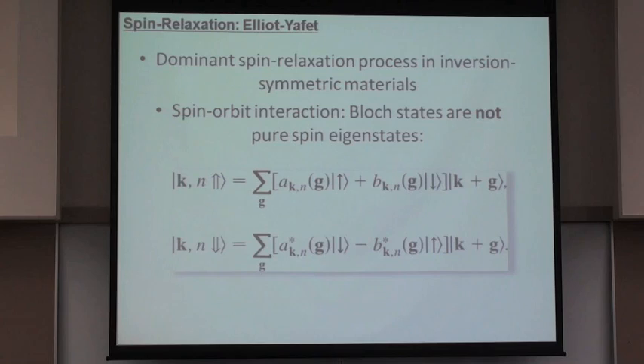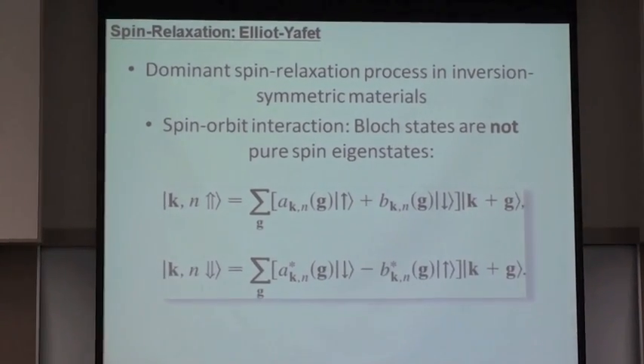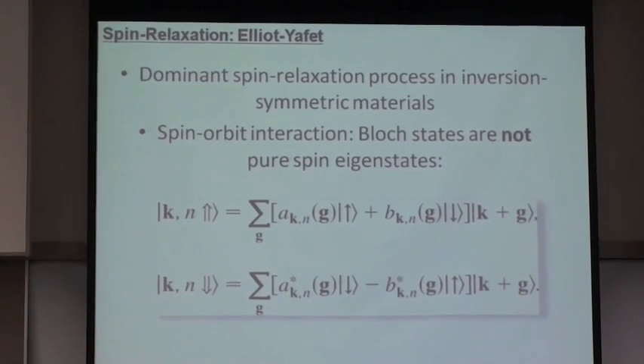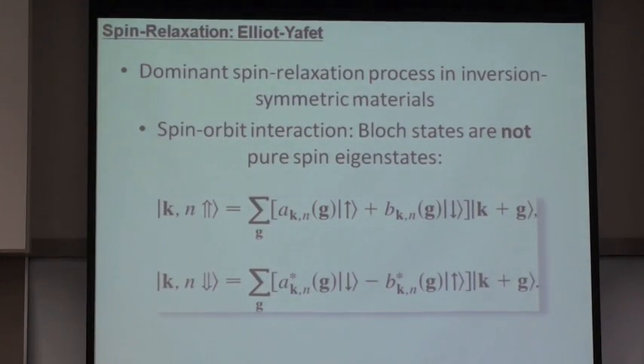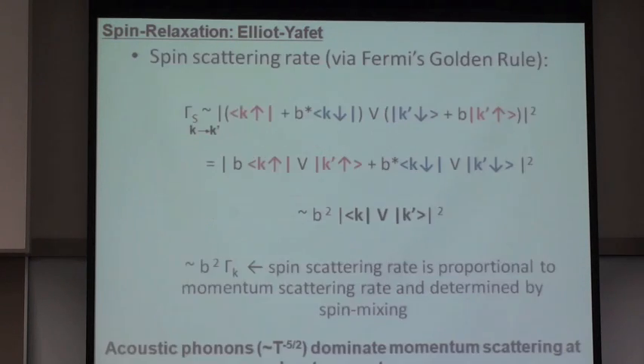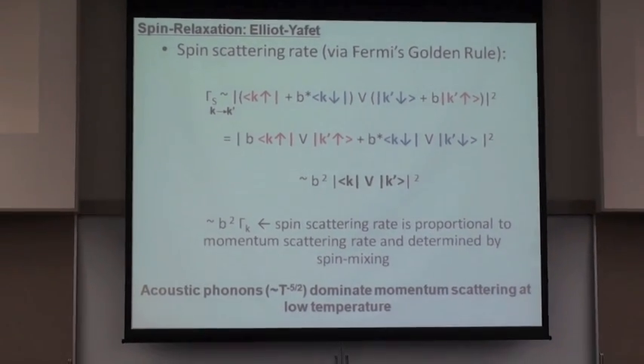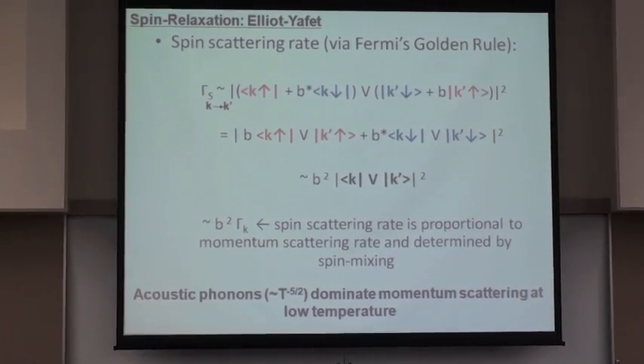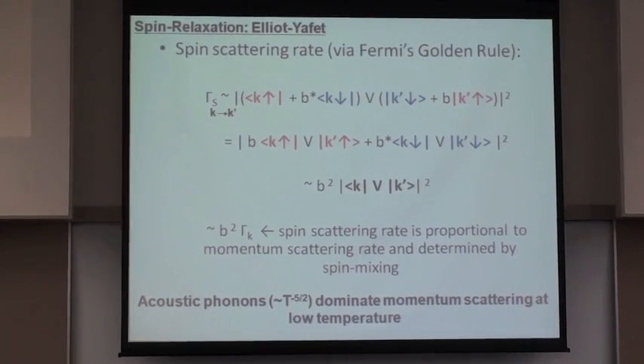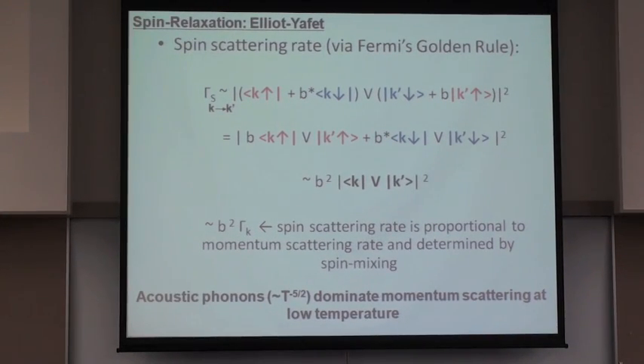This, as I described, the fact that the spin lifetime is finite is due to the fact that because there is a residual spin-orbit interaction, the eigenstates in the conduction band are not pure spin eigenstates. And what happens here is that the momentum scattering results also in a spin flip scattering that's proportional to that momentum scattering, and also proportional to the mixing amplitude of the opposite spin wave function. You can use this simple kind of idea to determine the power law due to the presence of acoustic phonons, which cause intravalley scattering in the silicon, that determines the spin lifetime at low temperatures.